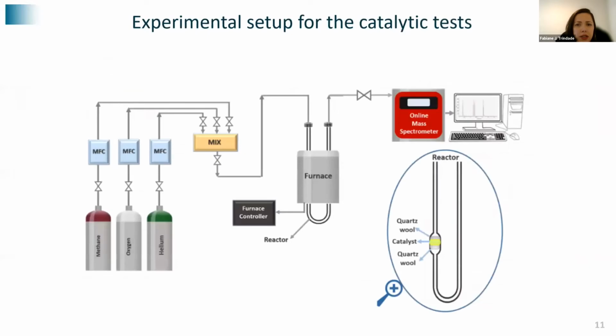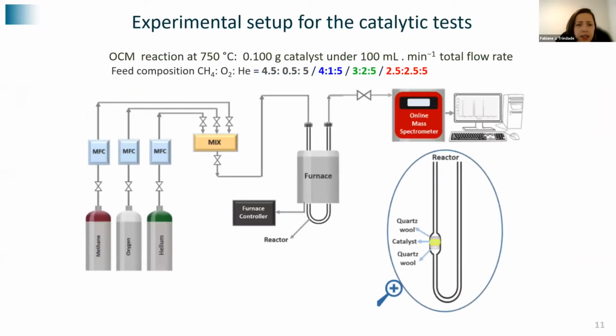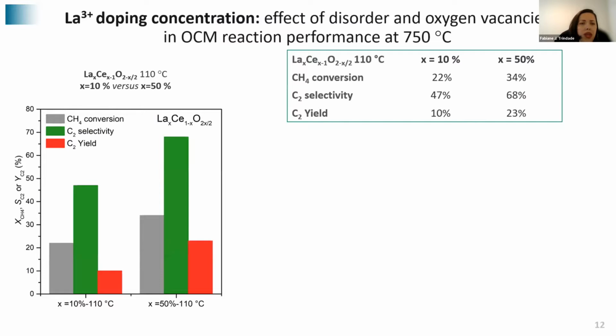So this is our experimental setup for the catalytic tests. Our reactants were methane and oxygen, diluted in helium, and this reaction was performed at 750 degrees. And this reactor was coupled to an online mass spectrometer so that we could monitor this reaction very fast and see the changes. So here we first analyzed the effect of lanthanum doping in the Ceria nanoparticles, how the amount of the dopant will influence the catalyst.